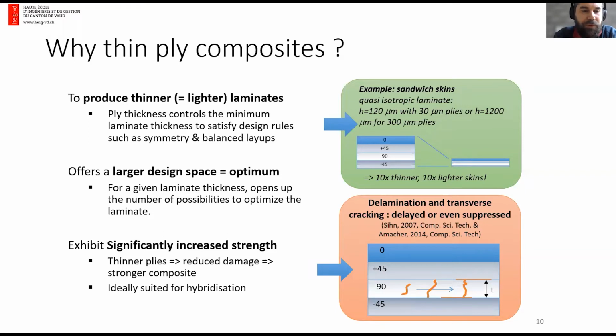Another type of advantage is based on the design flexibility of Thin-Ply. For a load-bearing structure several millimeters thick, we have a much larger design space to optimize the laminate. So we can achieve much more oriented or orthotropic laminates without compromising the symmetry and balance rules that we typically have in the aeronautic industry. And finally, last but not least, Thin-Ply Composites offer much improved resistance to transverse cracking, and so they can be used to a much higher stress level without inducing damage. That's probably the most interesting aspect. I will detail this a bit further in my talk.